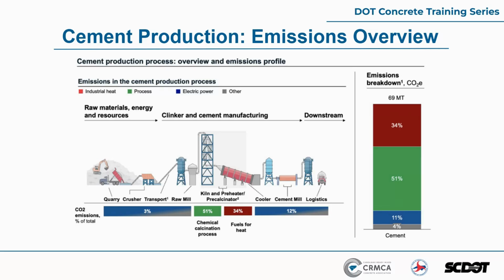But here you can see as it goes through the chemical calcination process, which means it goes through the preheater and precalcinator, you can see that that energy ramps up to 51%. And then as it's coming through the kiln, it consumes 34% of that. So 85% of our CO2 emissions at a cement plant takes place in that very process.